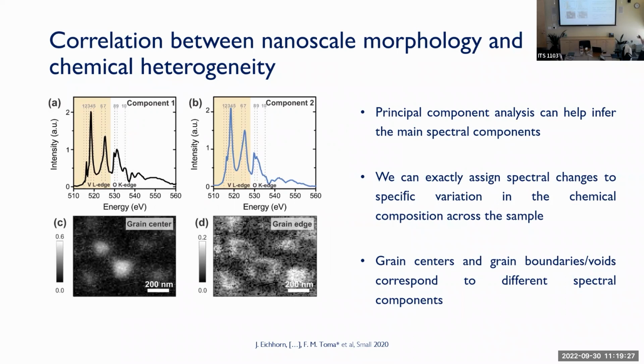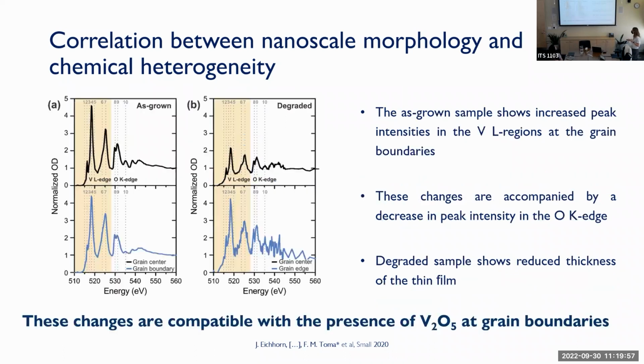And of course, we started biased because we knew that there was something going on at the electrolyte electrode interface. But by doing the principal component analysis, we basically took away our bias and we asked the algorithm to calculate for us what the different components in the spectra were. And by principal component analysis, we did find indeed that these two components are related to grain centers and grain edges. And what's special about this is that at the grain edges, and you see it,